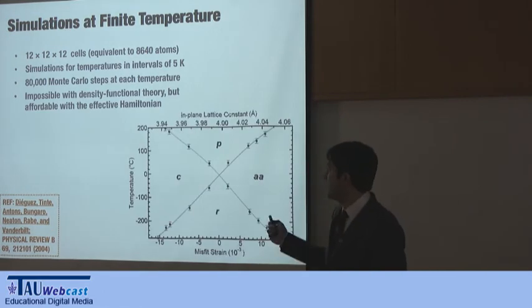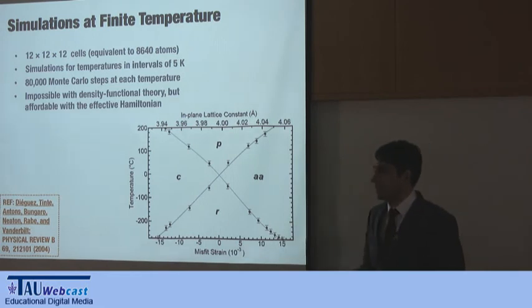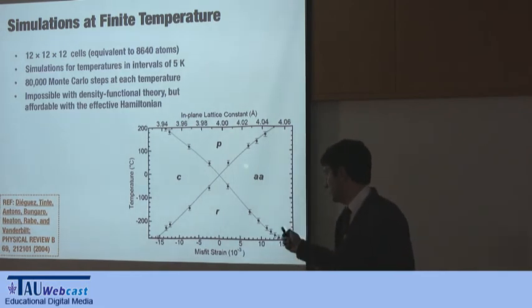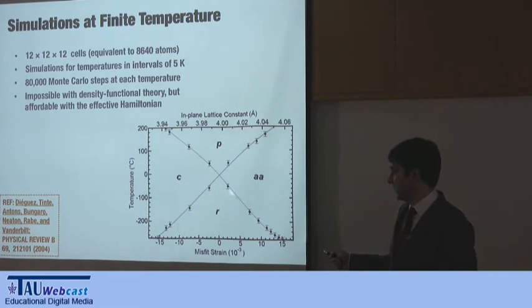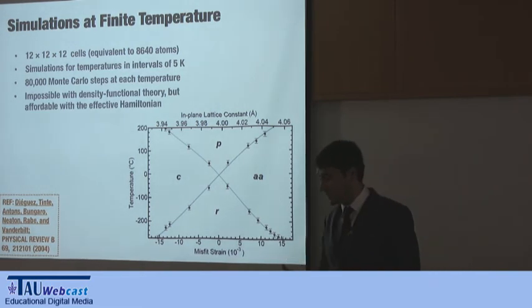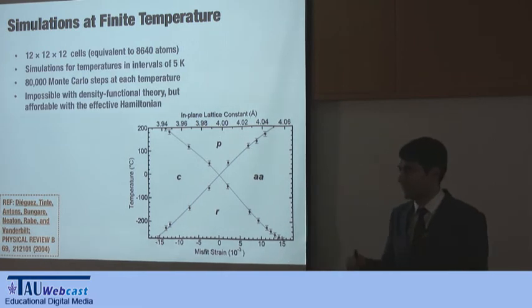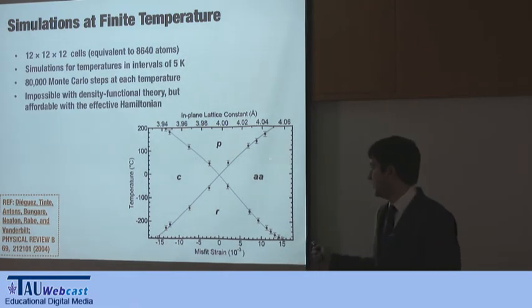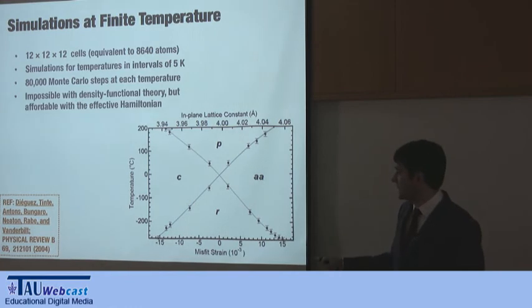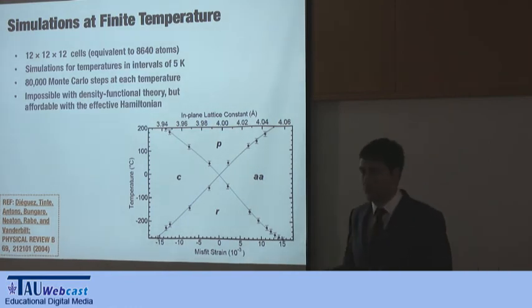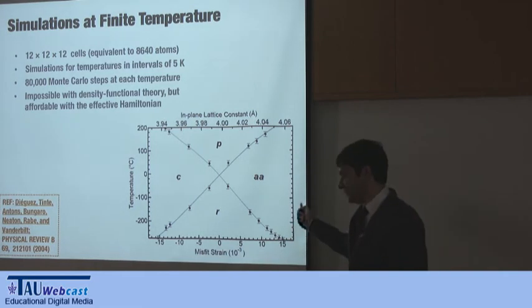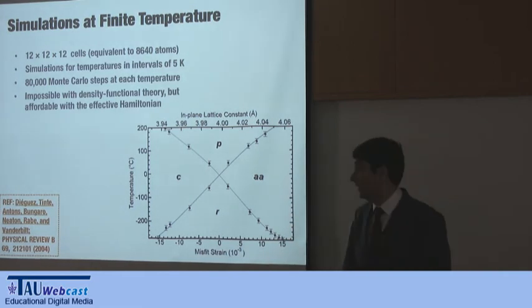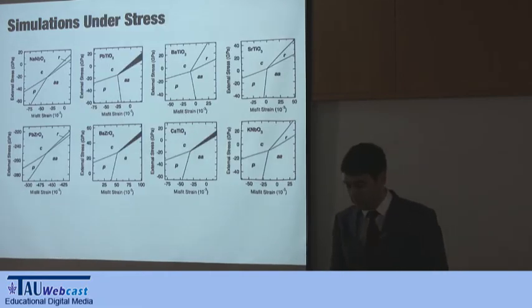I'm not going to give details. The point is that you can compute a phase diagram at a finite temperature. And then, again, you see different phases, but you can see that it's possible to do calculations based on DFT and finite temperatures. If you look at experiments, it's not easy to measure exactly where the polarization points to. It's easy to measure if there is a polarization or not, but where it points to is difficult. It seems that for what I know about barium titanate, this is quite accurate, other than the diagram is shifted, which has to do with shortcomings of DFT. But it's a tool to study these materials.